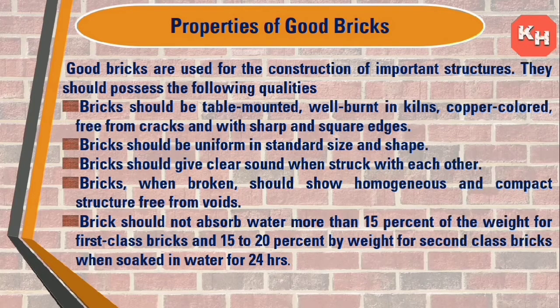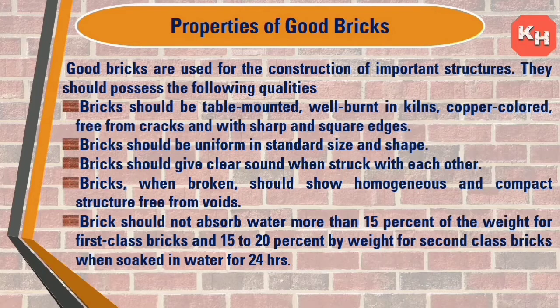Bricks should not absorb water more than 15 percent of their weight for first class bricks, and 15 to 20 percent for second class bricks, when soaked in water for 24 hours.